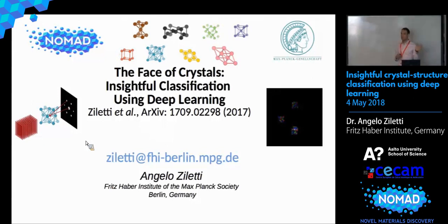Because actually the definition of a crystal is a well-defined diffraction pattern, otherwise you have a quasi-crystal. So with atom probe data, is that really a crystal, given that there's a lot of error in the experiment? There are two things. One is a real crystal, which we try to classify. Another is that there are errors in the resolution that are much higher, and it should look amorphous, because some atom tomography data look amorphous. So to classify this data, we need more work. But to answer your question, up to 10% of the lattice, we are able to classify very well.